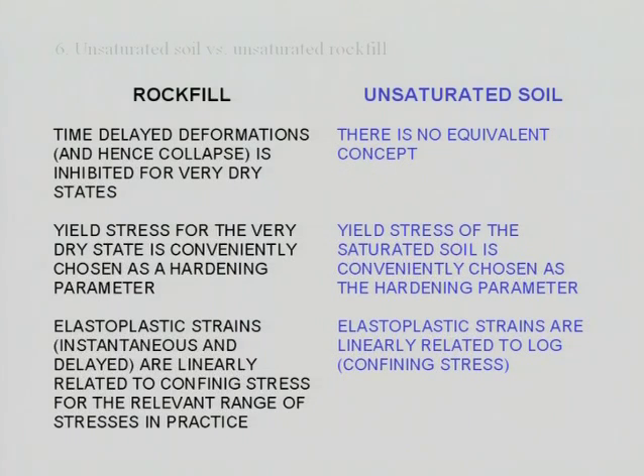Now, delayed deformations and therefore collapse, because collapse is explained as an acceleration of deformations, is inhibited for the very dry state. There is no such equivalent concept in soils. And the final 2 comments here are perhaps of less importance. We found that the yield stress for the very dry state is a conveniently hardening parameter. In general, in unsaturated soil, the yield stress for the saturated soil is a good hardening parameter in terms of formulating the equations. And elastoplastic strains tend to be related linearly with stress in the case of rock, and they tend to be, as we know, linearly related with the logarithm of stress in the case of soils.